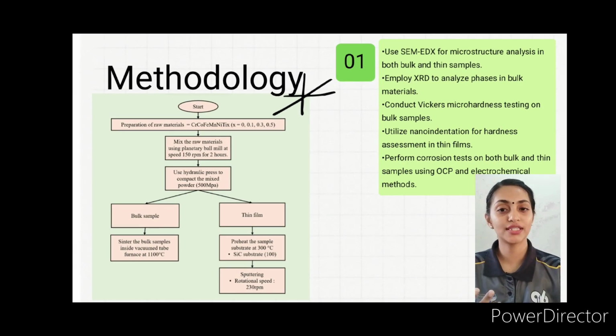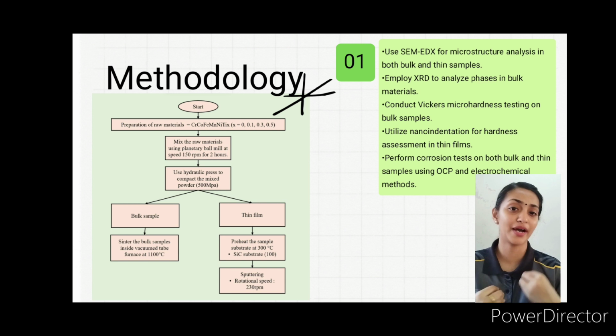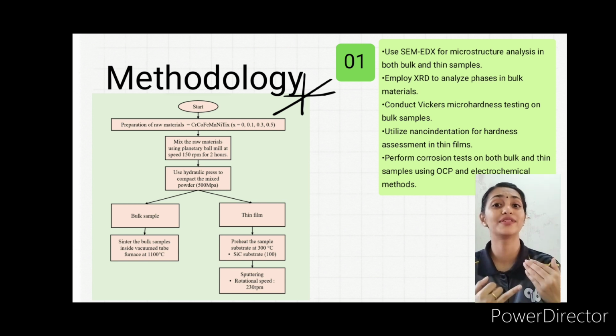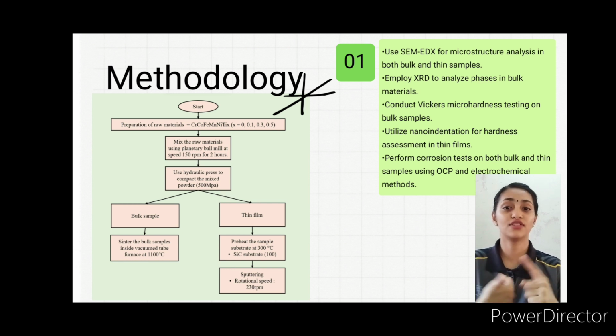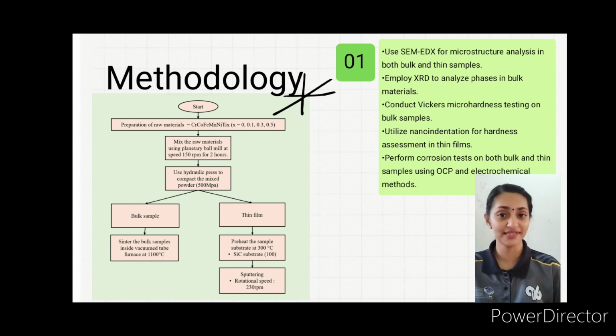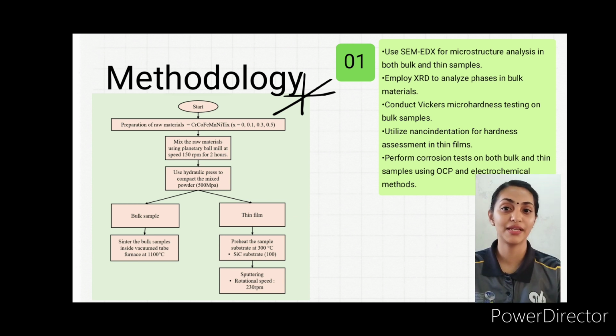Now we will look at the methodology, how I will conduct my research. First I will start by preparing the materials, where my material consists of Cantor alloy doped with titanium at different percentages such as 0.1, 0.3 and 0.5%. I will start with raw material. We will take out the powder and mix it using planetary ball milling at speed 150 rpm for 2 hours. Then I will use a hydraulic press to compact the mixed sample to produce the bulk sample. For the bulk sample, we will sinter it using a vacuum tube furnace at 1100 degrees Celsius.